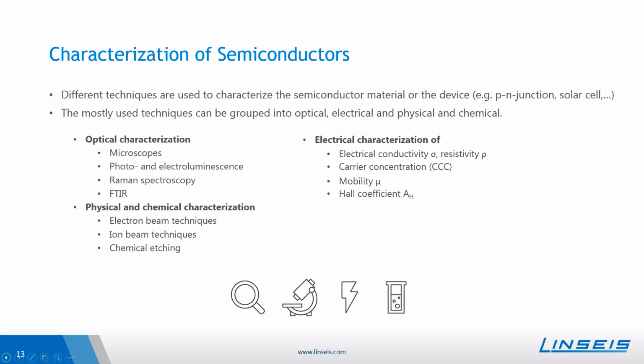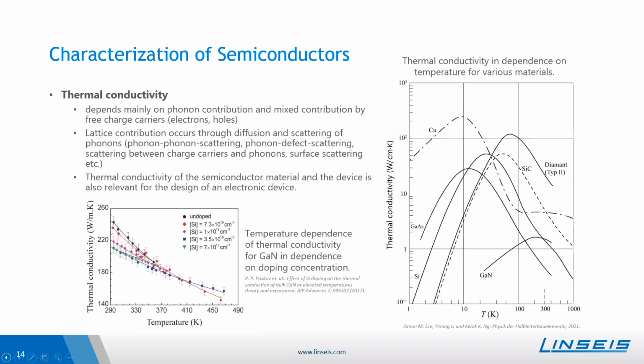So in general, the characterization of the properties of the raw material and also the device is important, as the properties can vary strongly with doping, but also with temperature. In the next slides, there are some examples. So for example, the thermal conductivity. In general, the thermal conductivity of a semiconductor depends mainly on the thermal conduction by phonons and the mixed thermal conduction by free charge carriers, so the electrons and the holes. There is also a lattice contribution to thermal conduction. It occurs through, for example, diffusion and scattering of phonons. Scattering events include, for example, phonon-phonon scattering, phonon-defect scattering, and scattering between phonons and charge carriers, boundaries, or surface scattering.